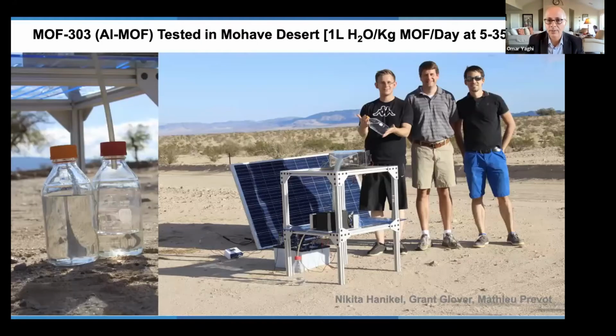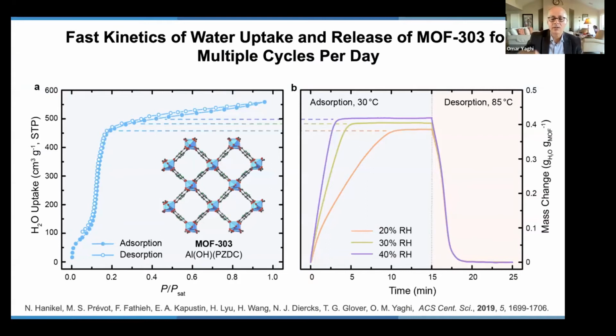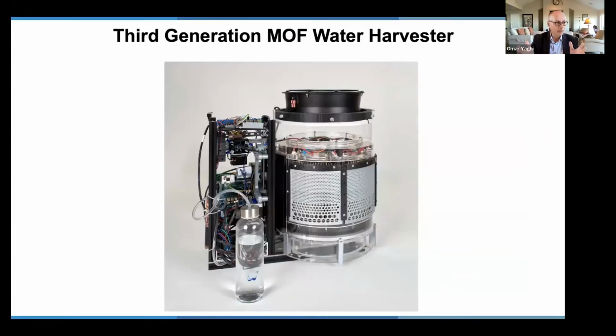So we collected 1 liter of water per kilogram of MOF per day. And that's because we can push air through by a fan into the MOF and do more than 1 cycle a day. So based on these fast cycles, you can remove the water within minutes. You can design another prototype that delivers 4 to 5 liters a day. But that's based on only 200 grams of MOF. This is 200 grams of MOF-303 gives you 4 to 5 liters of water.